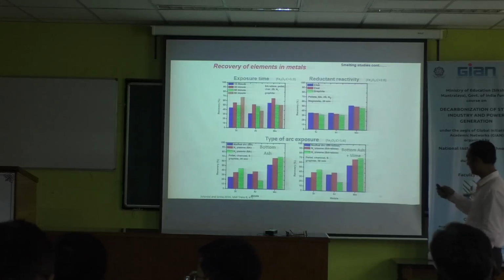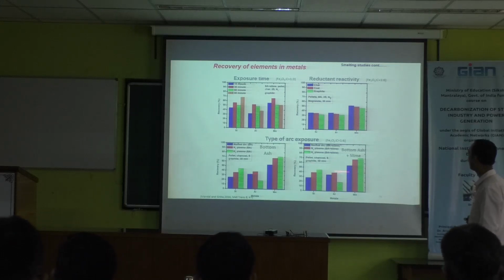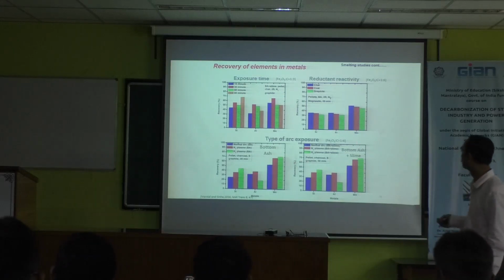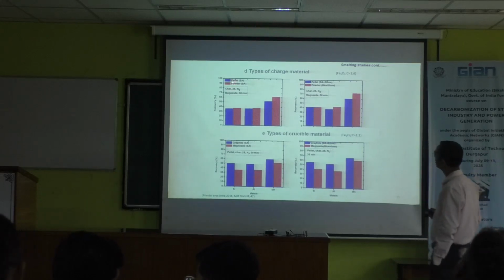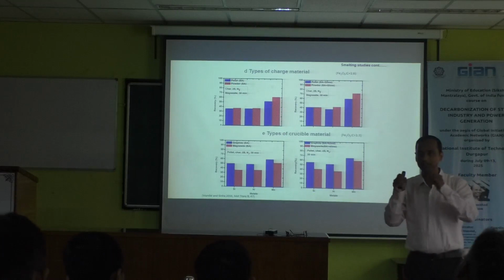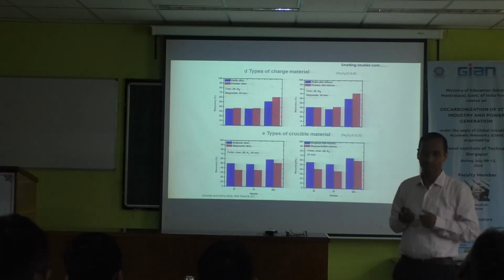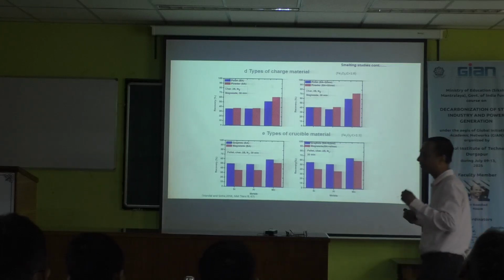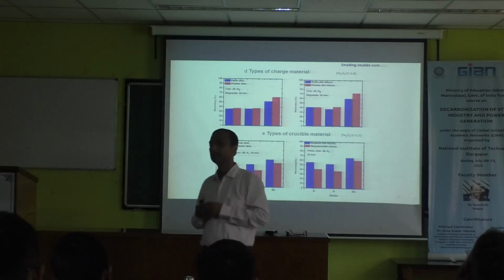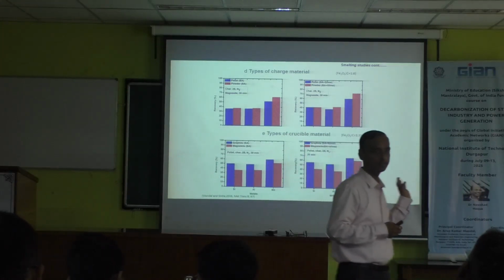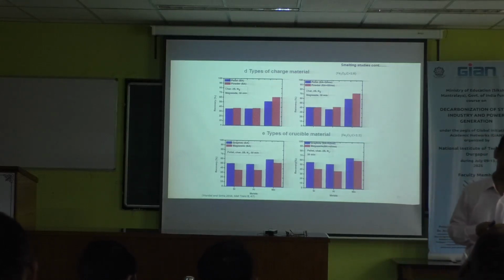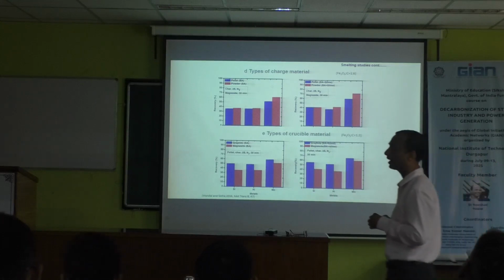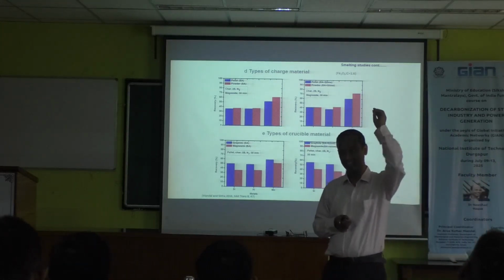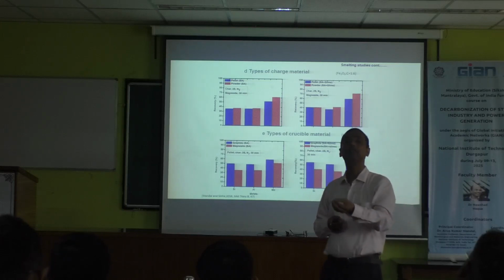If you see the exposure time, this is 10 minutes, 30 minutes, 60 minutes, 80 minutes. Silicon, aluminum, manganese, different metals are removed. This is the charge material, pellets as well as powder. You have observed that if you charge the pellet material, there will be less recovery as compared to the powder materials. Because in pellet materials the particle spacing is more, at high temperature specific metals like aluminum evaporate. Aluminum has a lower vaporization temperature. Therefore, at that temperature, if the metal is produced and you have provided intense heat, what will happen? It will easily escape out.